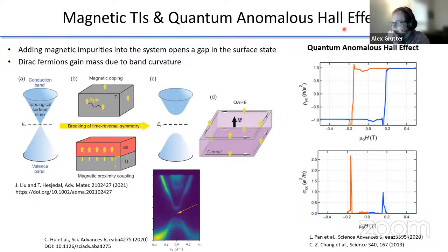And this is something that was originally demonstrated in 2013 by Cui-Zu Chang et al. And the basic idea is that, okay, you have your Dirac cone, your topological surface state, and you want to induce magnetization in this topological surface state, in the topological insulator. So bismuth selenide and bismuth antimony telluride, they're not naturally magnetic, but it turns out that you can dope them. So you put some chromium or vanadium dopants into the system, and you get a net magnetization. And what this does is break time reversal symmetry and opens up a gap in the surface state.